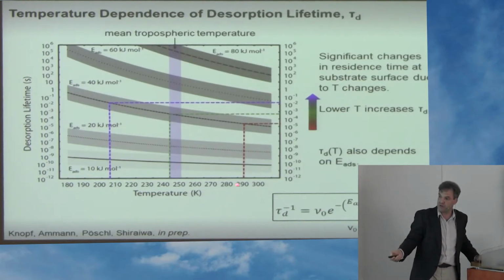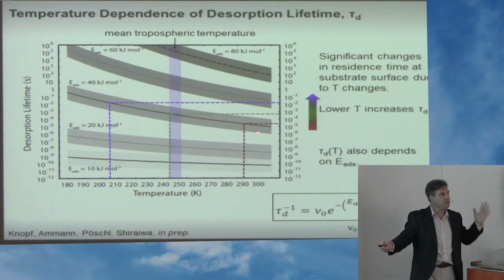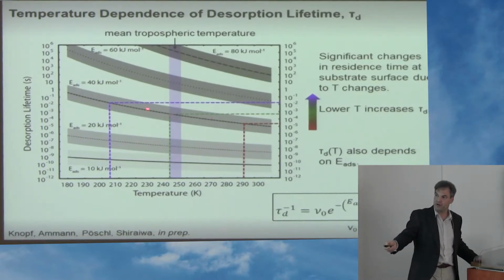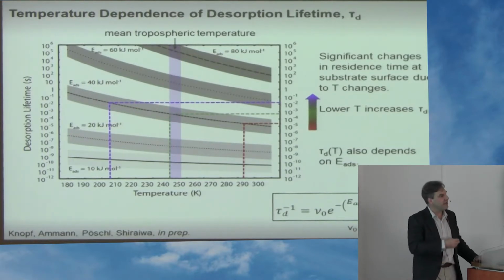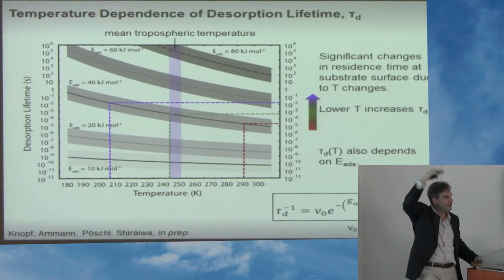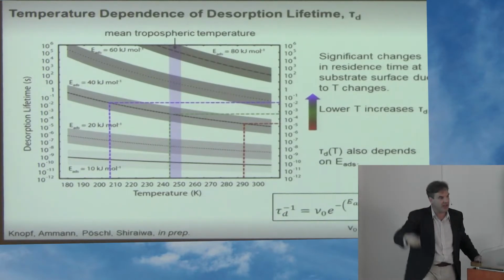And if you start putting the temperature dependence here, what you see is at laboratory conditions, maybe a millisecond, a microsecond - if it doesn't react in that time, it's not important. But if we go to lower temperatures, we gain orders of magnitude of lifetime. So it can completely change the chemical reaction pathways, what is really going on in the majority of the atmosphere.